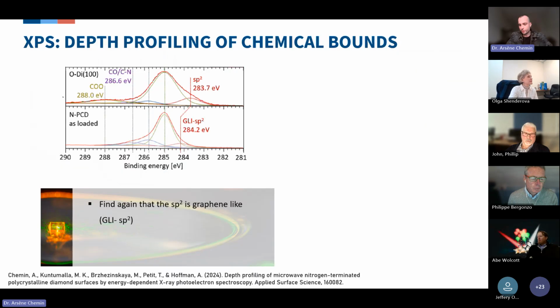So what we can do at the synchrotron, in contrast to the lab measurement, is that we can change the excitation energy of the X-ray. And that is particularly interesting because by doing so, we can probe different depths. Because if you change the excitation of the X-ray and you consider a given binding energy, for instance, the carbon is around 285 eV, you will change the kinetic energy of exit of the electron. And the escape depth of the electrons will depend on this kinetic energy. So the more energy they have, the deeper they escape from. And so we can really get very interesting information from that.